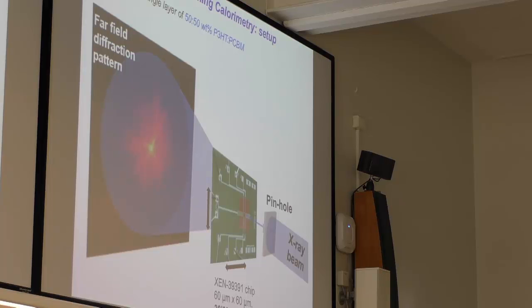But then when you consider it a bit more carefully, you can think that in this case, of course, the thermal mass is very small, right? That's the key to this. There's a really, really, really small thermal mass, and in the active area here, which is like 60 by 60 micron, there are some interdigitated electrodes providing power to this very thin silicon nitride membrane, and onto this membrane, a film of the order of 1 micron thick has been deposited, right? So you have a 60 by 60 by 1 micrometer cube